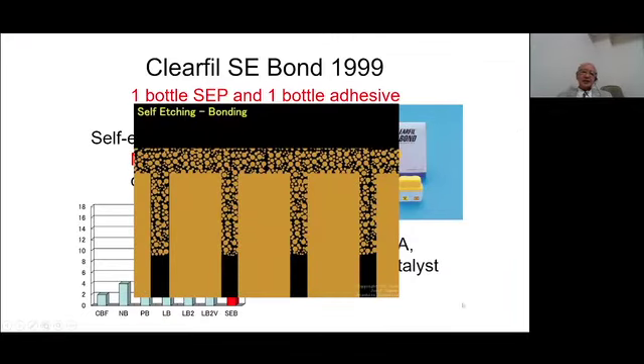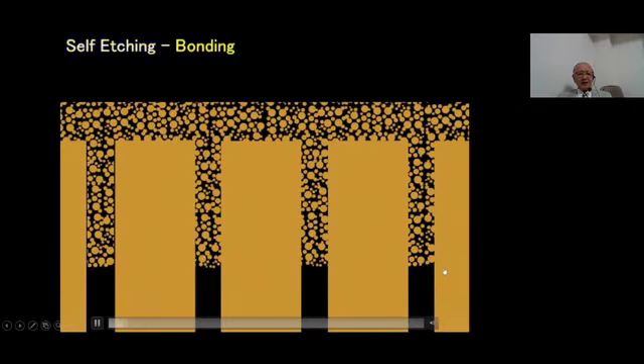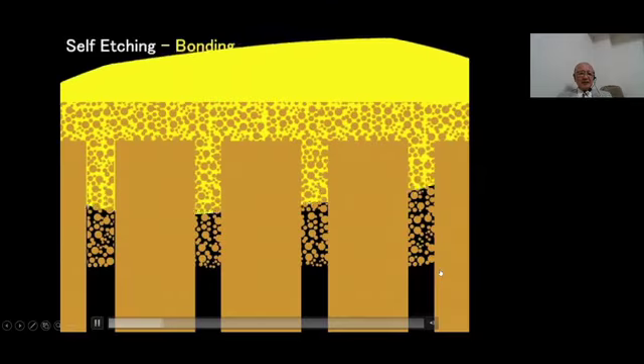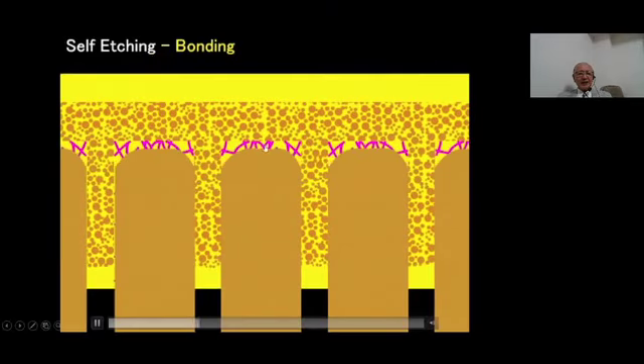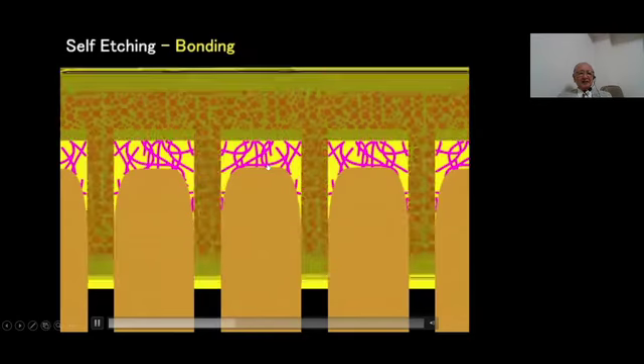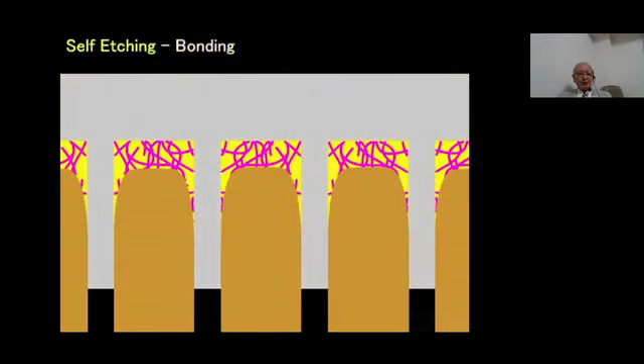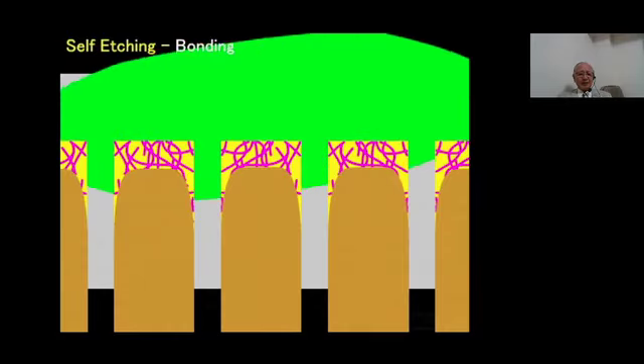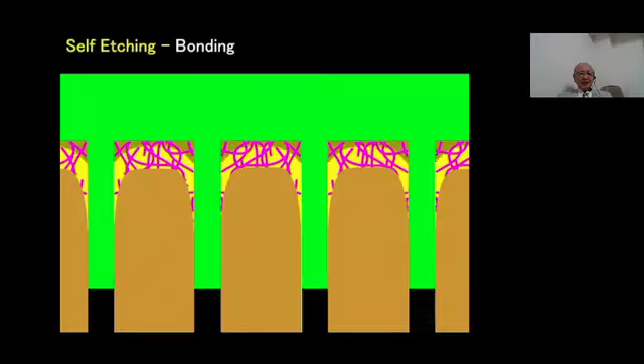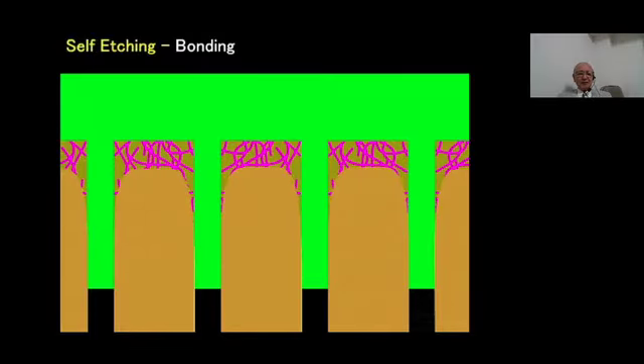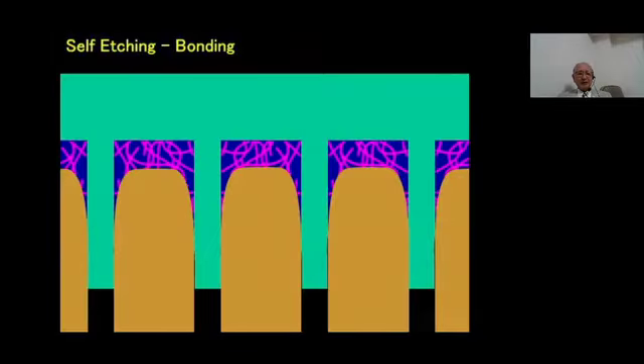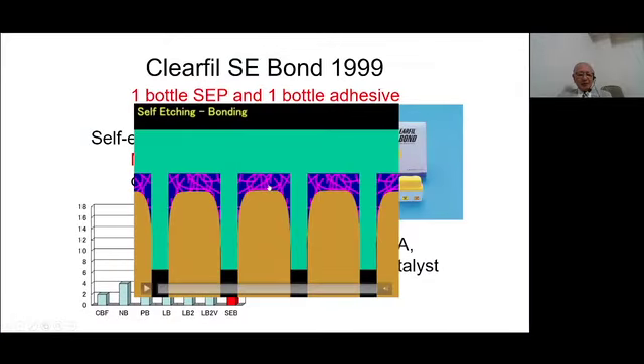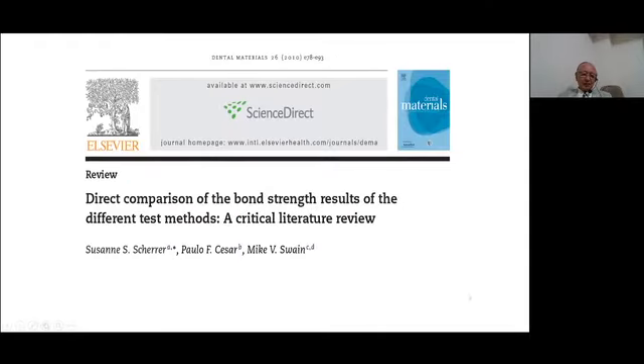So I show the animation movie of the bonding mechanism with this two-step self-etching material. The self-etching primer is applied. This is acidic enough to remove the smear layer, but the depth of etching is not so deep, and the collagen layer is already treated with a primer, that's why it does not shrink. Then the bonding resin can penetrate fully into the demineralized dentin part, producing the very excellent hybrid layer without any microspace. That's why this bonding interface is very durable and strong.